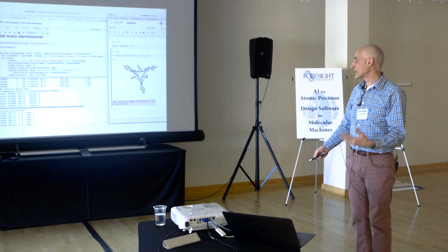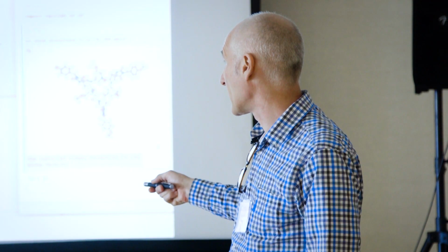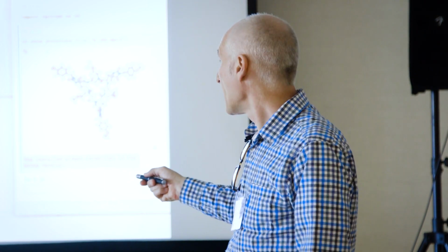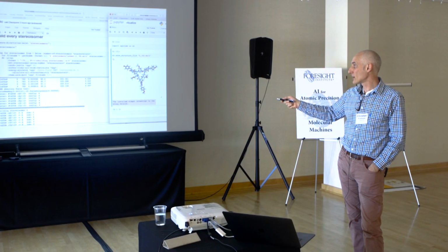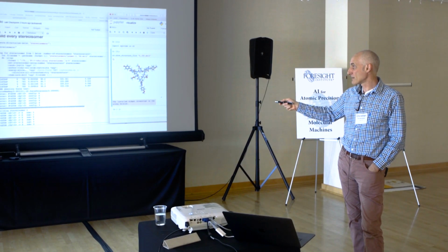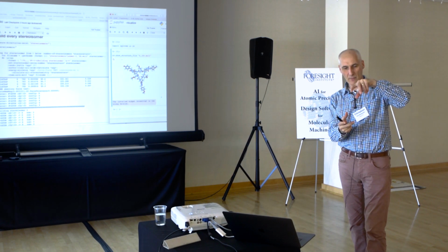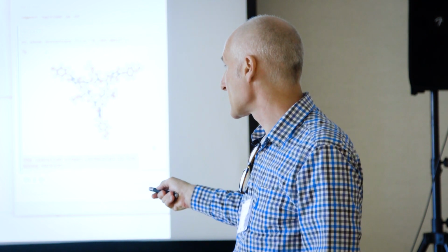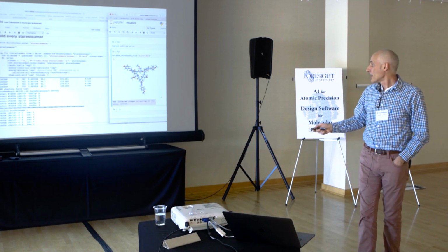And the way I'm setting this up is I can load that ChemDraw file into CANDO, that's what's running here. The user interface is what's called a Jupyter notebook, and you can write code in CANDO that will build every stereoisomer, do energy minimization on it, calculate whether the carboxylic acids that are generated match up to where they would need to be to bind the zirconium oxo cluster, and then iterate through them all, and then save the best fit. So you see the result of the calculation.